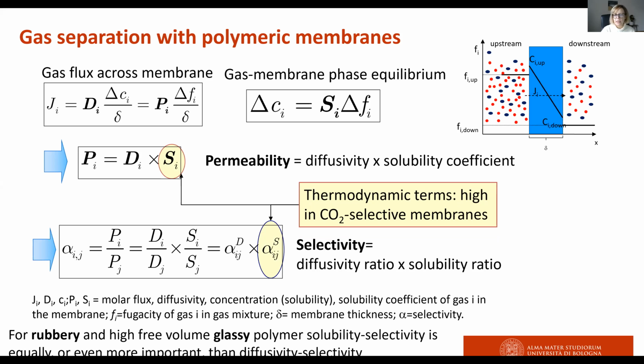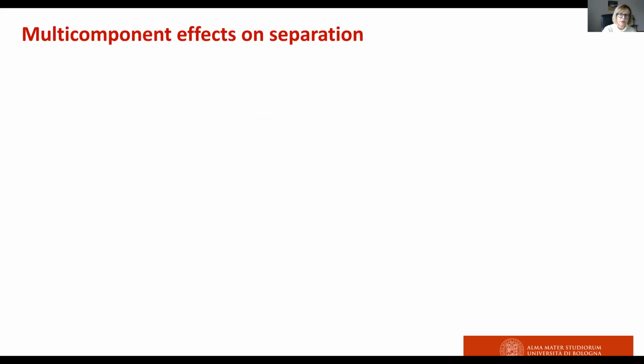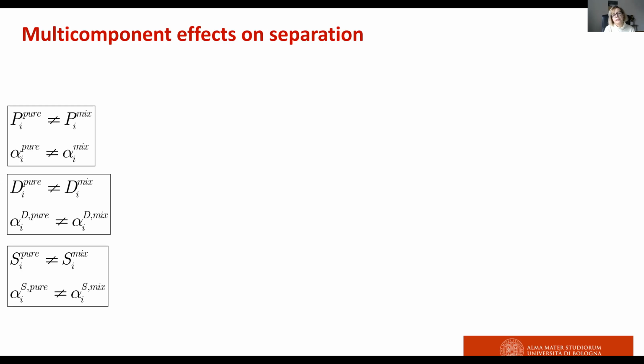Thermodynamics, of course, play a role in the solubility terms of permeability and of selectivity. It is also important to notice that most of the times membrane processes are designed using properties which are evaluated from experimental measurements carried out in pure gas conditions, while the real process involves mixtures, multi-component systems. So what you can see is that permeability, diffusivity, and solubility, and consequently also the selectivity, are different if calculated based on pure gas conditions or in mixed gas conditions.